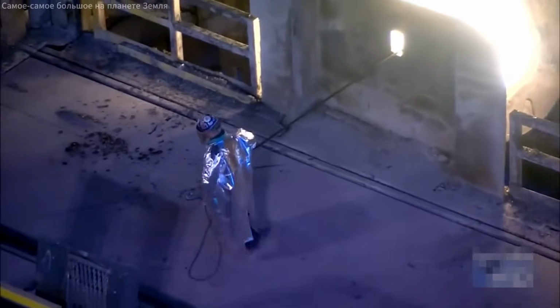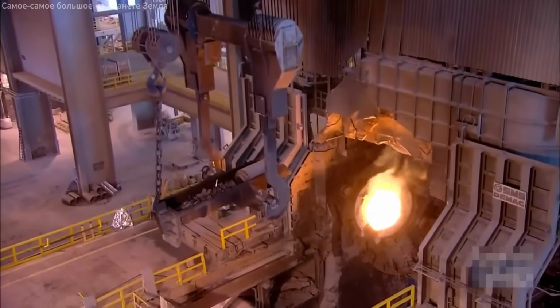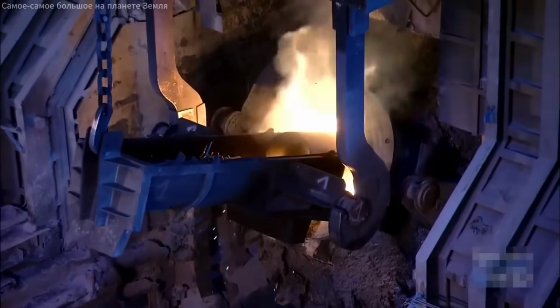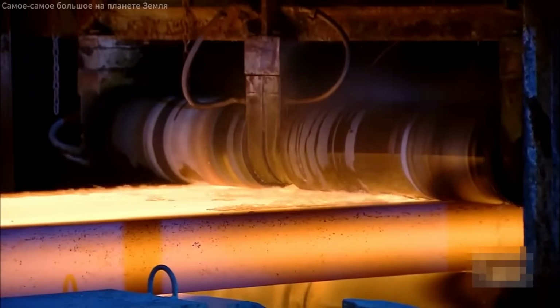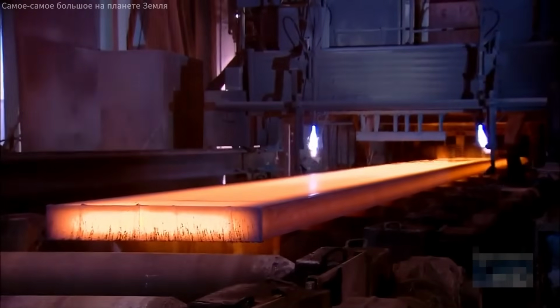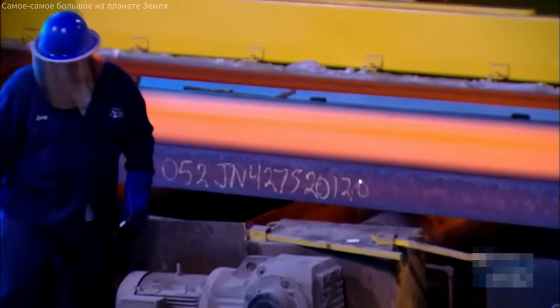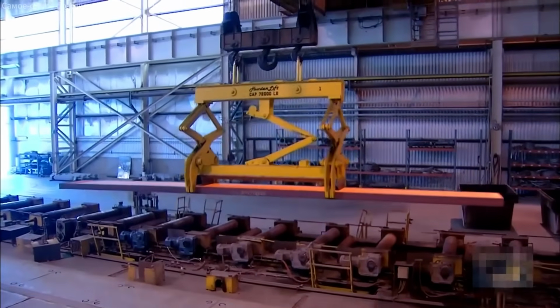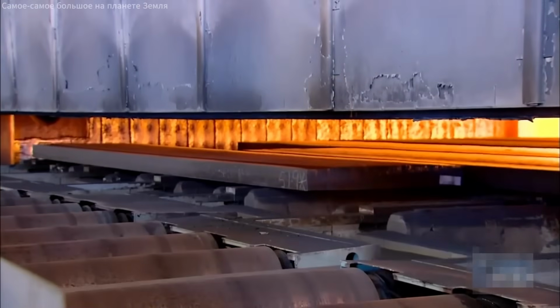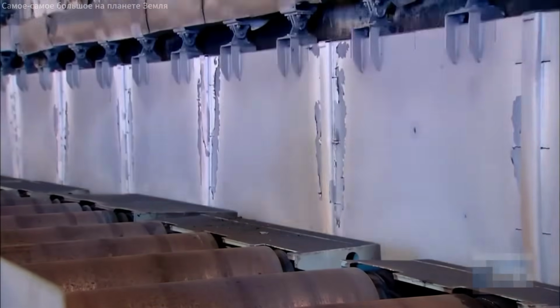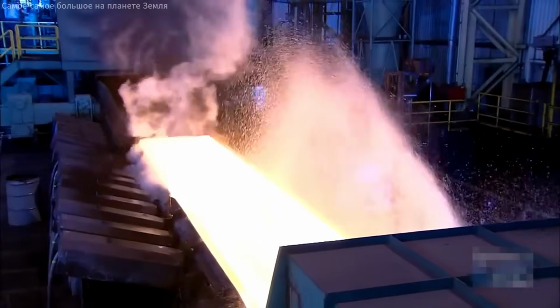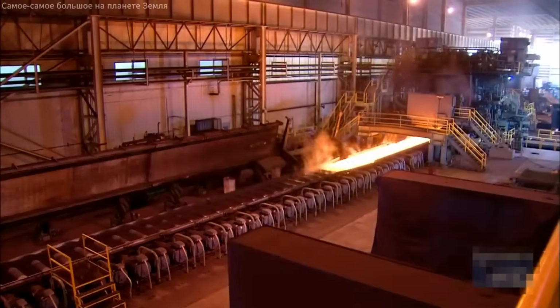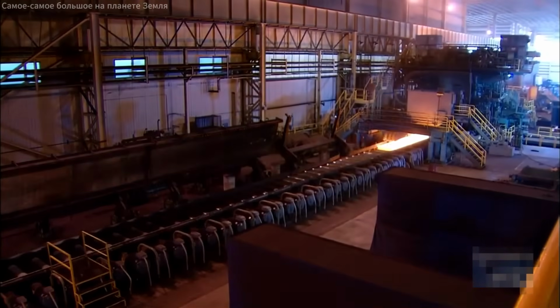After melting, the steel is refined by blowing argon and oxygen gases to remove impurities, which form slag and are discarded. Metallurgists carefully control temperature and chemical reactions throughout. The clean molten steel is poured into molds to form slabs or billets, then reheated to soften for rolling. Hot rolling stretches and thins the steel using water-cooled rollers, sometimes creating strips up to 600 meters long. The strips are cooled and coiled.